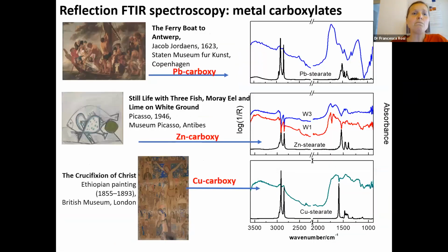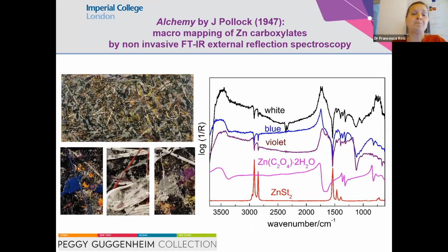But we are also very sensitive for the identification of another class of common degradation material, which are the metal carboxylates. We can distinguish the different types of metal interacting with the lipidic medium, even though the spectra appear in reflection mode and they are quite different with respect to the transmission spectra. We can recognize the different metal, the different type of carboxylate. And also the fact that we can make a sort of macro mapping of the distribution of such degradation